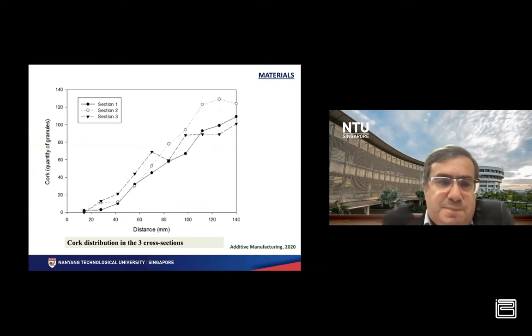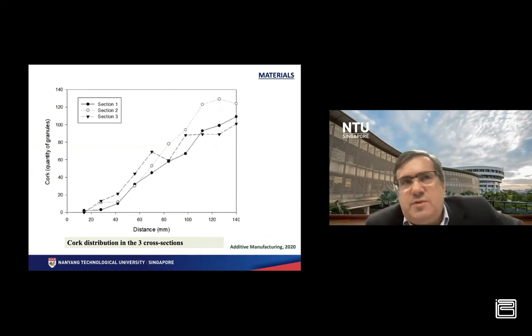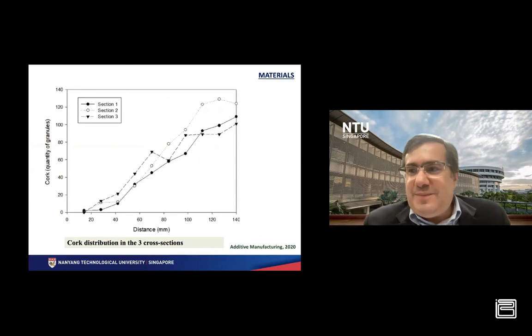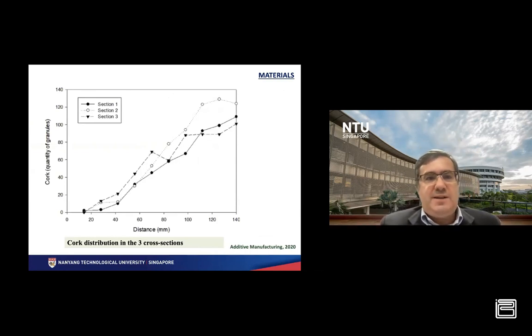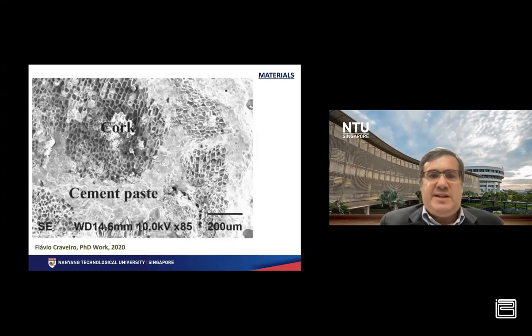in the printed structure. The advantage of cork, and so this was a collaboration with Corticeira Amorim, a company in Portugal, and basically we used very poor quality cork. But the relevance of using cork was not only because we were able to reduce the amount of cement, reducing the CO2 footprint, but also to improve the thermal performance of the construction elements. And we simulated that.